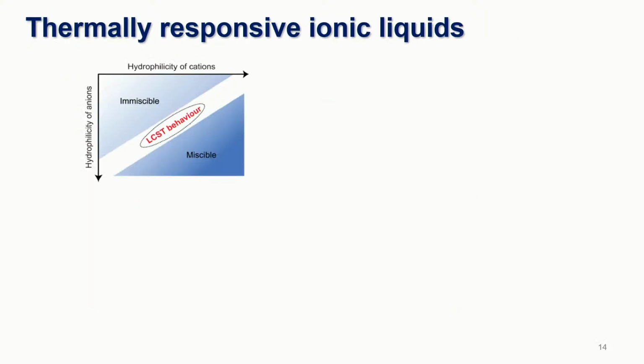And so here, looking at how do you get this LCST behavior. So really it's a combination of the material, the ionic liquid cation, and the anion has to have this very subtle balance in its hydrophobic and hydrophilic characteristics. Because if it's too hydrophilic, you get a very miscible solution. It'll never phase separate. If it's too hydrophobic, it'll always be two phases. And so there is this sweet spot, this region in between, that allows us to increase temperature and create the two phases.